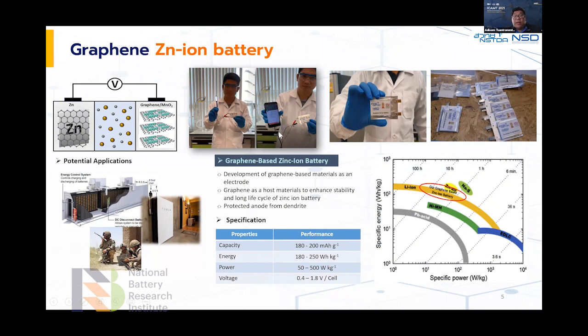And you can see that we successfully made a pouch cell out of it, and our capacity is in the range of 180 to 200 milliamp hour per gram, which is comparable to some of the lithium-ion battery. And also energy density is in the range of 180 to 250 watt-hour per kilogram. And the power is in the range of 50 to 500 watt per kilogram. And the voltage is up to 1.8 volt per cell. And you can see that if we put in the Ragone plot that I previously showed you, our graphene zinc-ion battery is about here. So it has the same performance as the lithium-ion battery in terms of the specific energy and in terms of the specific power.